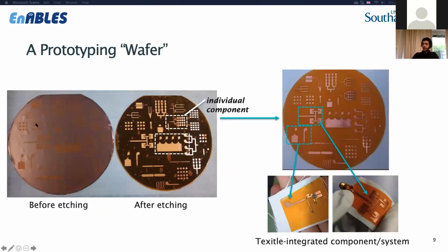So what this looks like is we normally have one 6-inch or 8-inch wafer. You have multiple designs, multiple individual components in this wafer. We etch them individually, and then we cut the entire thing into smaller pieces. We assemble it and integrate it with textiles. We usually use heat pressing or vacuum forming to integrate flexible polyimide circuits into textiles for wearables. And therefore, we can have components or complete systems which can be fabricated using a straightforward method which accommodates multiple designs and allows faster prototyping.